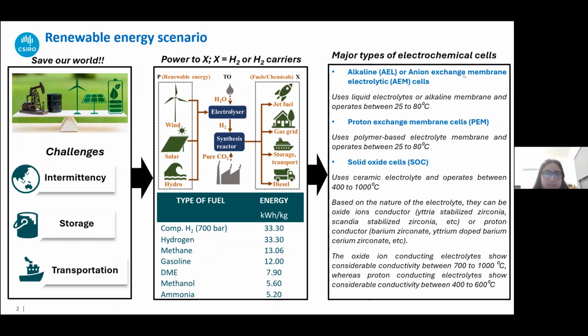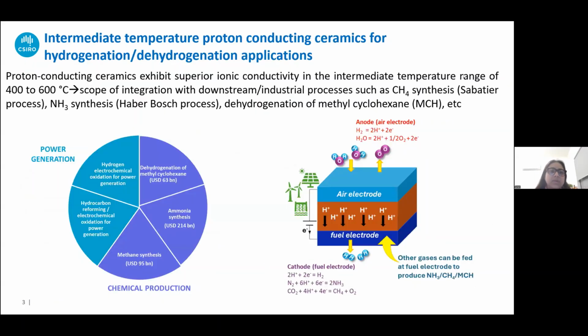One is the pure oxide based, where the electrolyte that we use is an oxide ion conducting ceramic material like yttria stabilized zirconia or scandia stabilized zirconia. These materials show appreciable conductivity in the high temperature range of 700 to 1000 degrees. Whereas there's another category where the electrolyte is a proton conducting ceramic material, which shows sufficient conductivity in the intermediate temperature regime of 400 to 600 degrees. In today's presentation, I'll be mainly focusing on this intermediate temperature proton conducting ceramics for different hydrogenation, dehydrogenation applications.